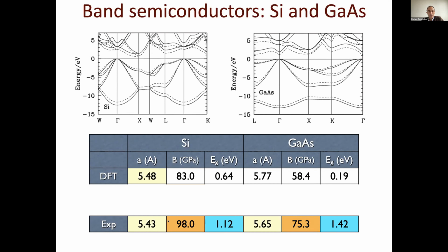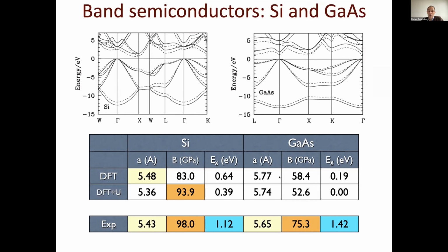So you see here the experimental value for all these quantities, and how close or how distant the GGA prediction is. And the +U, of course, can only improve some of that, but fails in improving the band gap, just because favoring basically integer occupation on each site suppresses the hybridization between sites, which is so important for this material, where the band gap is basically between bonding and anti-bonding states.